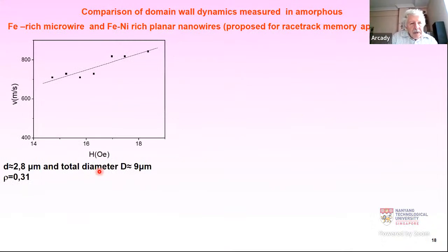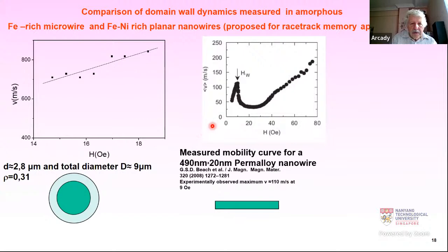So now if we compare the domain wall dynamics, the dependence of the domain wall velocity on magnetic field, for one of the thinnest samples which we studied, about 2.8 micrometers, with thin nanowires prepared by a sputtering technique, we can see that in our case the domain wall velocity is usually, even without any additional treatment, about one order higher than in nanowires, for example, Permalloy nanowire.